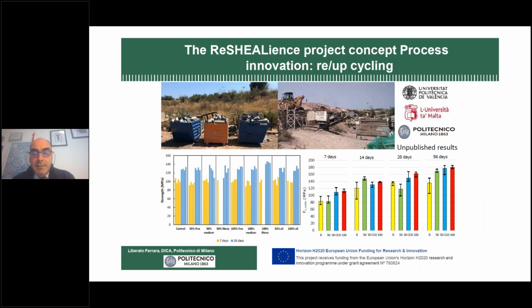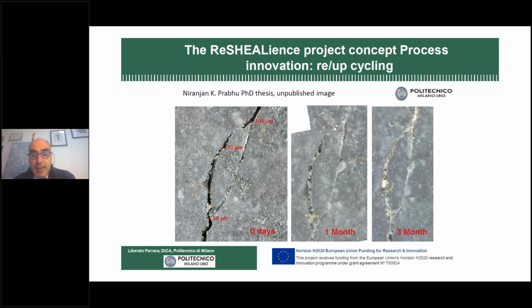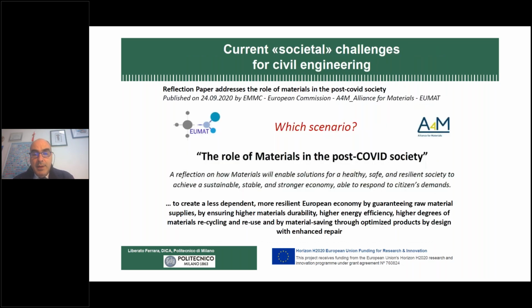the yellow one, all the materials employing recycled material as aggregates were able to guarantee higher, if not comparable, compressive strength, flexural strength as well. But also, these are results of PhD theses going on now, we're also able to guarantee the persistence of the healing capacity also upon recycling. So which is the final scenario?